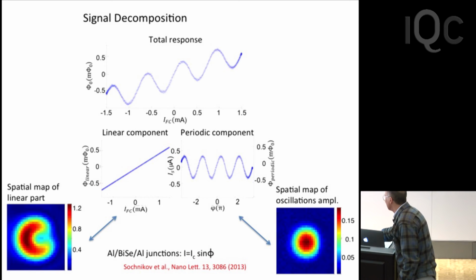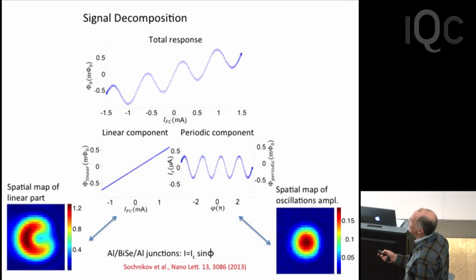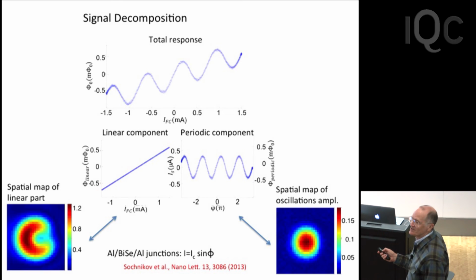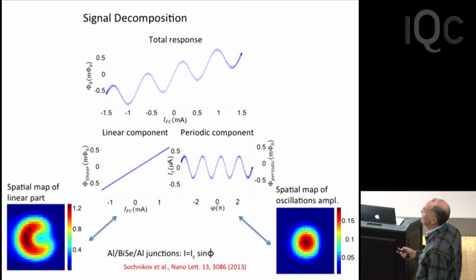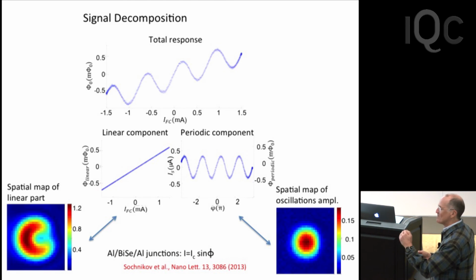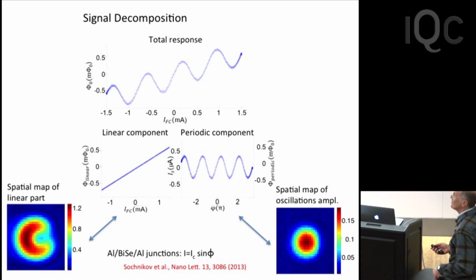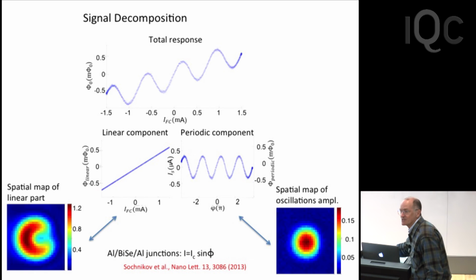Oh, yeah. And the bottom line, and this took out about 10 slides from my talk, is that this is very sinusoidal. It's very conventional. And what we think is going on is that if you look at photoemission results for the bismuth selenide, the Fermi level is actually in the conduction band, so that there are lots of bulk states, and they're just sort of swamping out anything that might be going on from the topological insulators.